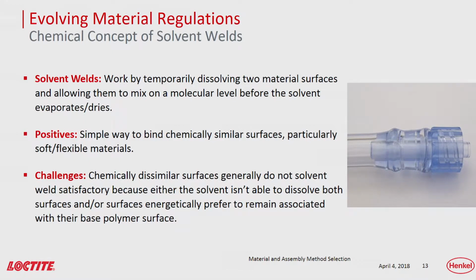A little bit of information about solvent welds. Plastics, depending on the plastic, will have a certain degree of solubility in different solvents. A solvent weld works by taking two different substrates and putting a solvent between them that partially dissolves each surface. So it partially dissolves the surface of substrate A and partially dissolves the surface of substrate B, and as the substrates partially dissolve on their surfaces, the interface is allowed to mix, and then the solvent is evaporated, leaving substrate A, an interface that has both substrate A and B, and then substrate B.